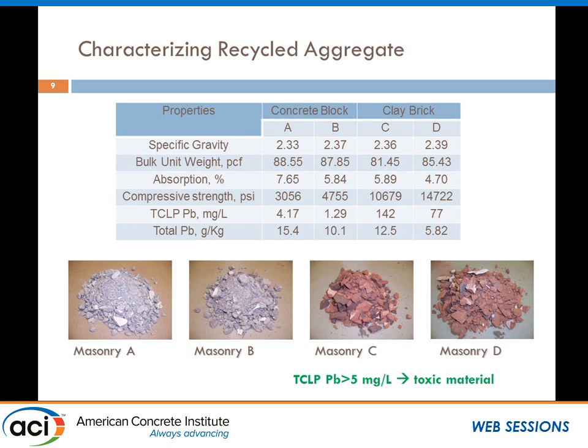Another thing is that when we use concrete masonry, the material we get is actually in better shape compared to clay brick. Most of the clay brick, especially those bigger particles, because they're brittle, are irregular in shape, so might not be that good for concrete use. And if you see the next few slides, when we talk about gradation, they have more coarser particles.